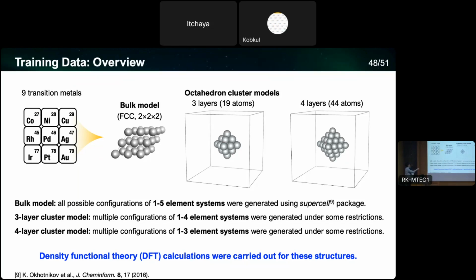And from these 9 elements, we put some number of elements in the bulk model or clusters. So here is the summary of our dataset. For the bulk model, we consider up to 5 elements, which is already the high entropy alloys. And using the package called supercell to consider all the possible configurations. From a combination of some number of elements that we put into the model, we performed density functional theory calculations, including structure relaxations, for all the possible combinations.